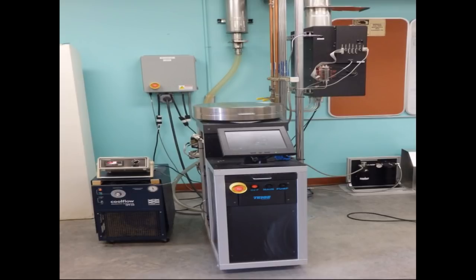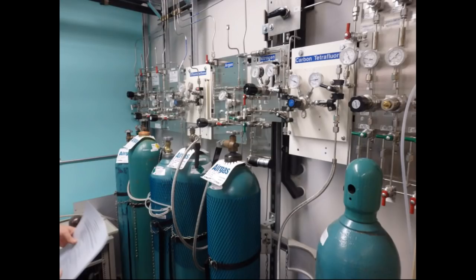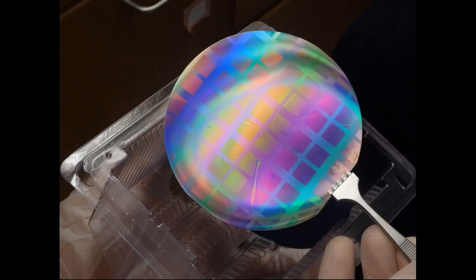If we used acid, it would etch the sides of the pores in addition to etching downwards. The walls between the pores would likely be eaten away, leaving no pores at all. The system uses a plasma with different gases to get different effects. One gas etches, and another grows a plastic on the side of the pores. This method also applies in a single direction, so it's perfect for this application, and it's called the Bosch process.